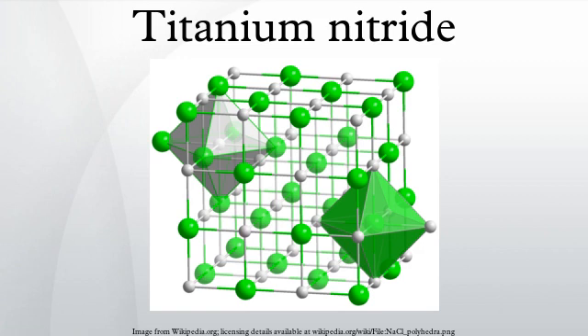As a constituent in steel making, titanium nitride is also produced intentionally within some steels by judicious addition of titanium to the alloy. TiN forms at very high temperatures because of its very low enthalpy of formation, and even nucleates directly from the melt in secondary steel making.